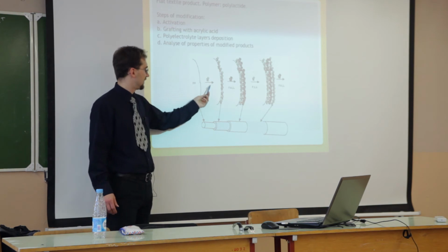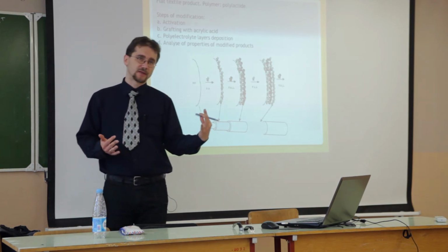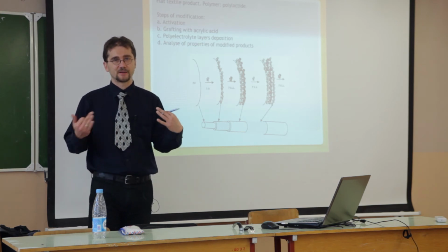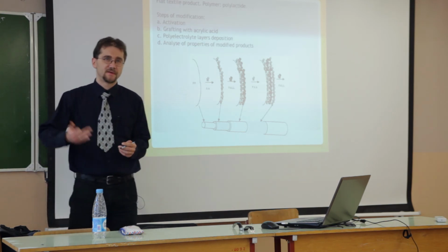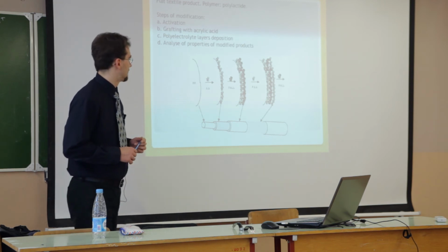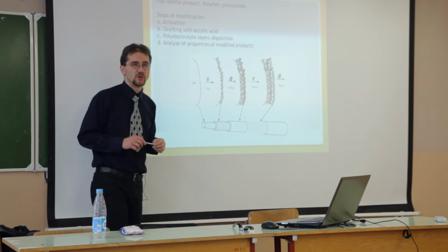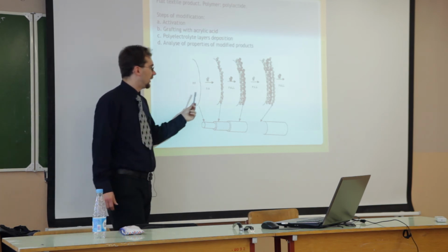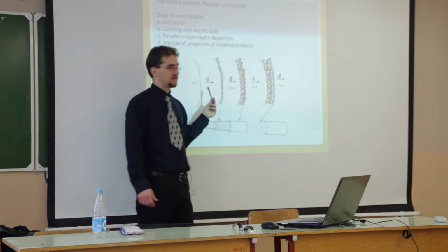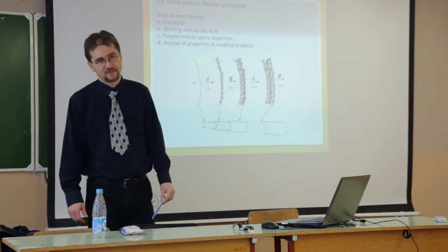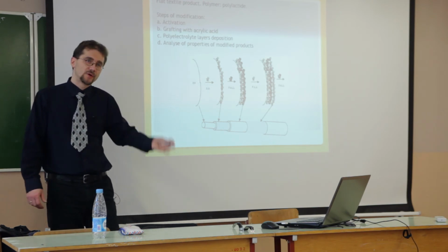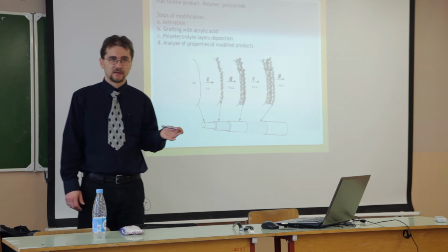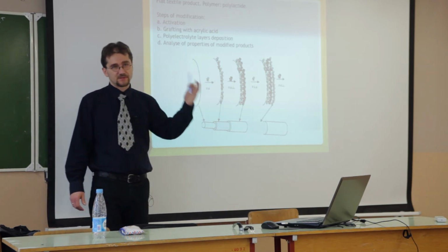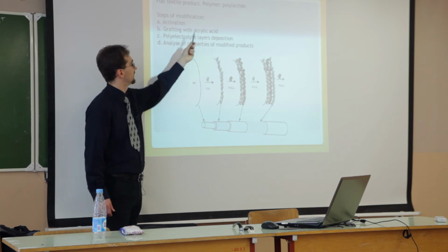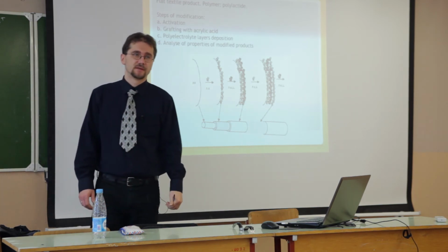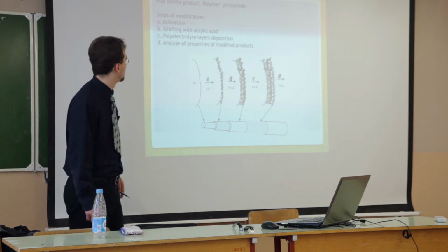The first stage, and this is the main problem with the application of layer by layer, is that we need to find some method to introduce the first layer. In polypropylene, and also polylactide, we use a grafting process. So layer by layer deposition itself is very easy, very cheap, and very fast, but there's always a problem with introducing the first layer. So we have to use the grafting process, a two-stage process, activation and grafting, both stages at 80 degrees, as you saw about the grafting.